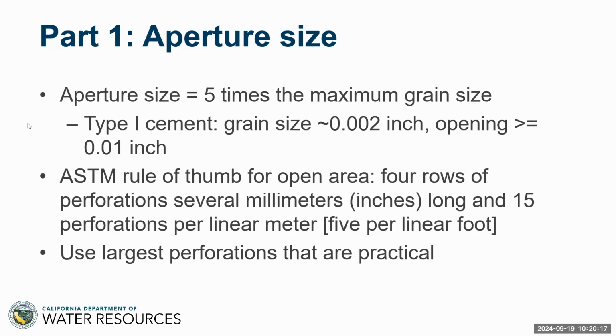Okay, so the first part of James's excellent question, aperture size. He noted correctly that there doesn't seem to be any quantitative backup to what people have been doing for years. The way I looked at it is this: if you look at the grain size of the grout, we know from Fisher grouting, which is basically the same as trying to push grout through the slots there, that you have to have an aperture that's at least 3 to 5 times bigger than the maximum particle size of the cement. So in a typical type 1 cement, the largest 10-15%, which control penetration, the particle size is about 0.002 inch. So if you take the rule of 5, that means that the opening has to be bigger than 0.01.